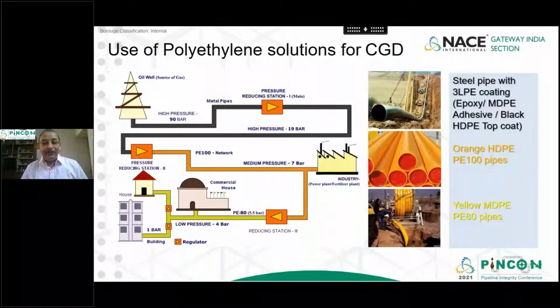Coming to my topic today, polyethylene is used in different parts of a city gas distribution network. The first part is the high pressure network, where the pressure can be anything between 19 bar to 90 bar. There, steel pipes with three-layer polyethylene coating are used. The three layers are epoxy, MDPE adhesive, and polyethylene top coat. In the distribution network for medium pressure lines, orange PE100 HDPE pipes are used up to 7 bar pressure. And in the last part of the network, in last mile connectivity, yellow MDPE PE80 pipes are used, which are for lower pressure and smaller diameter pipes.